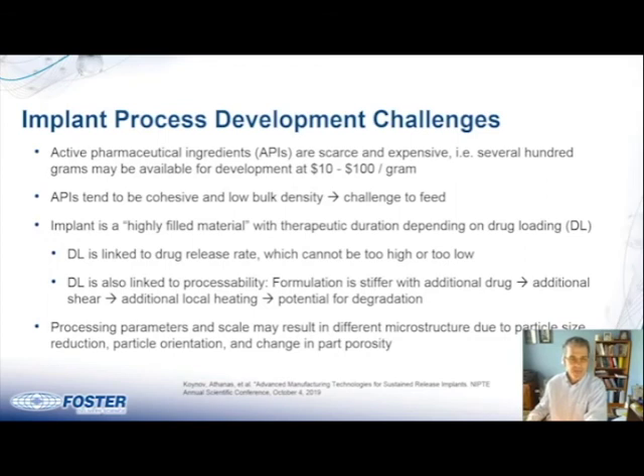The implant is a highly filled material with a therapeutic duration that depends on the drug loading. So the drug loading is linked to the release rate, which cannot be too high or too low. If the drug loading is too high, then it leads to processing issues and you really can't process the material. And if it's too low, then you won't achieve the desired drug release rate.